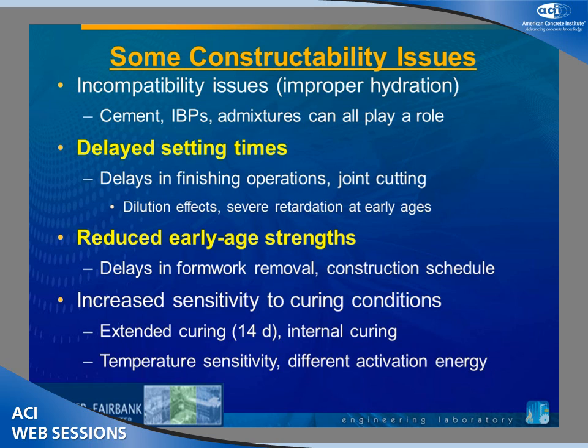One of the ways that that's accounted for in Portland limestone cements, for instance, when you have the dilution, is you grind finer to get the early age properties up. So the industry is very good at finding ways to get these new concretes to approach the ordinary Portland cement concretes that they're used to. Another